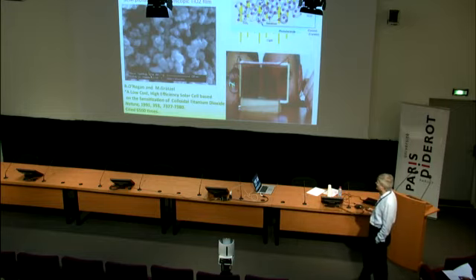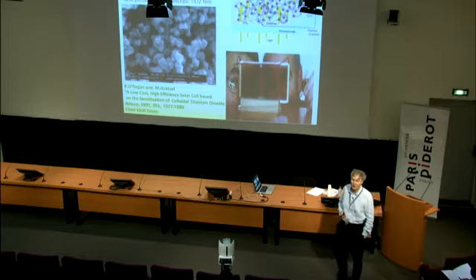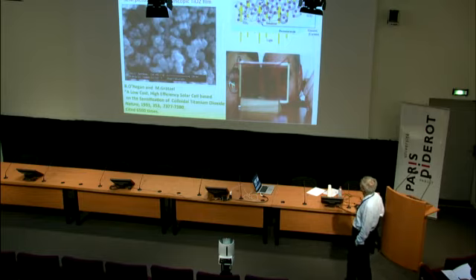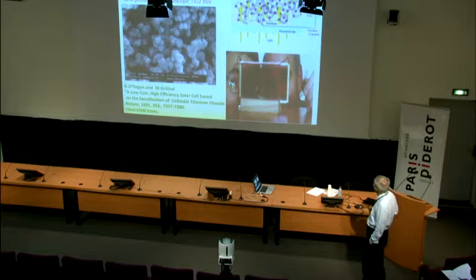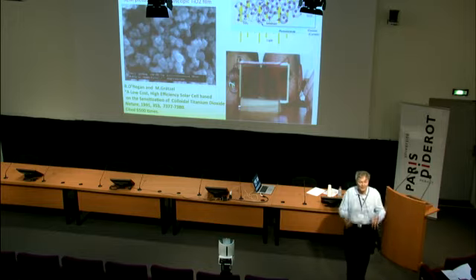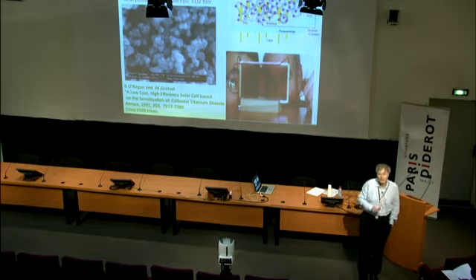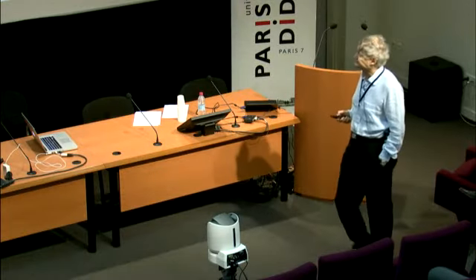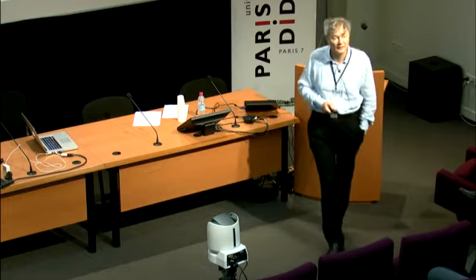But the amazing thing is that yes, we have a disordered structure. These are TiO2 nanoparticles here, about 20 to 30 nanometers in size. And the porous space is filled by an electrolyte or a hole conductor, organic or inorganic. This makes a three-dimensional junction, and the sensitizer is placed on this film by a self-assembly process. Just dip the film in the solution, and the sensitizer goes on. It has attaching groups that make it interact with the TiO2 surface, and that is a self-limiting process. That's very nice. It would be very hard to get that monolayer of sensitizer on unless you had a self-limiting process.